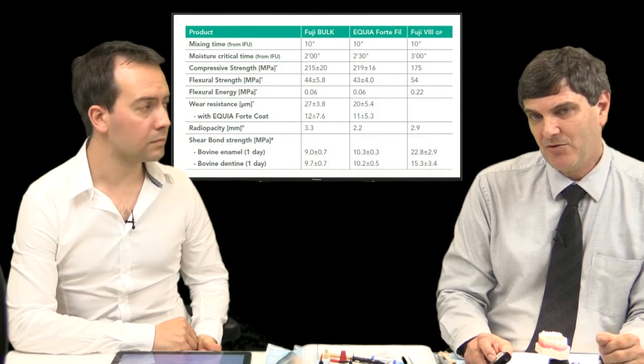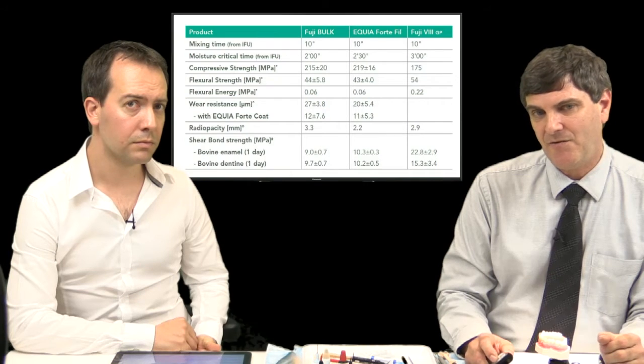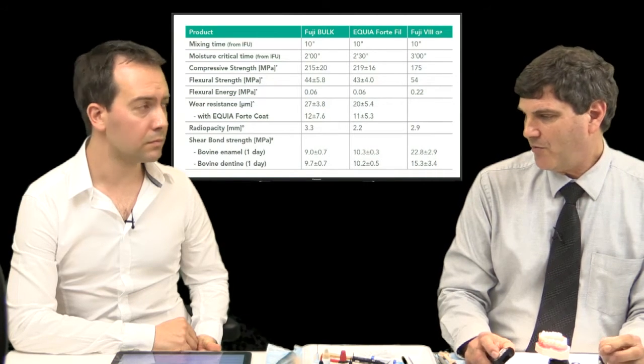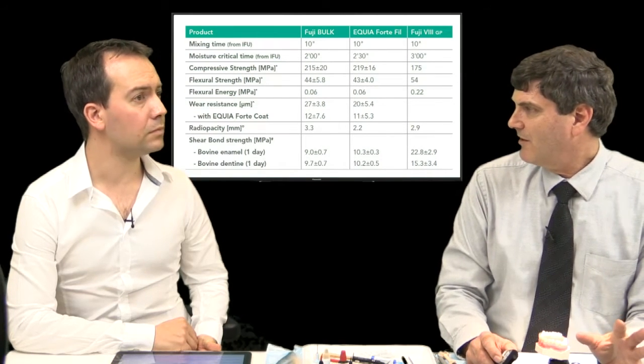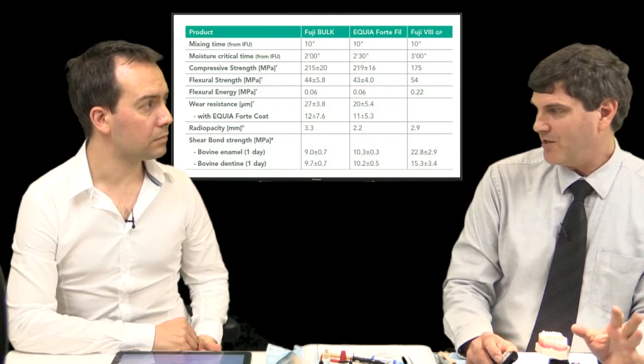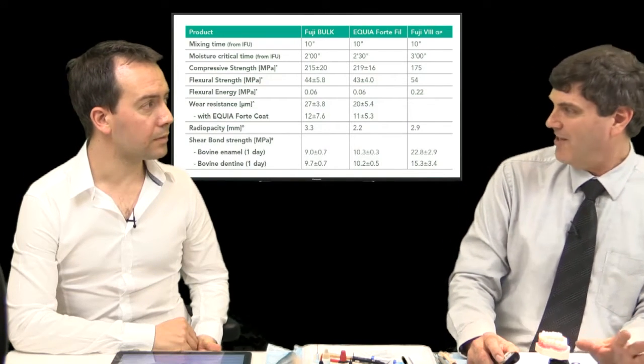But being a fully chemical set material, the Fuji 8 has a fairly long moisture critical time. You've got to wait 3 minutes before you can get any moisture near it. And in fact, you need to wait 6 minutes before you can start trimming and polishing it. Now that's an eternity in clinical practice.